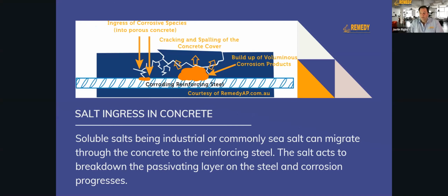Coupled with that is where salt enters. Salt can migrate through the concrete and find its way towards the steel. And whether the concrete's high pH or if it's carbonated, it doesn't matter. The salt will still interrupt that passivating layer and cause corrosion in alkaline concrete. If the salt migrates at the same speed as carbonation, it just means when they both get there, it's going to be very aggressive corrosion.